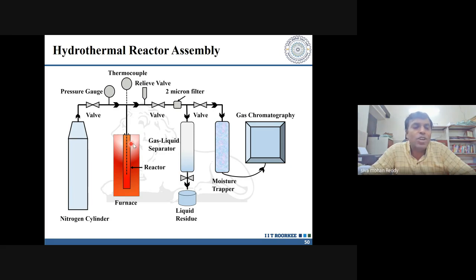Before we place the reactor inside the furnace, we make sure that the inlet valve and the outlet valve over here are closed. As a result, it forms a closed system, and when you heat it, the pressure is automatically built up inside the reactor. As soon as you are heating, the supercritical state is going to be achieved after some time. Once the supercritical state has been achieved, from the pressure gauge we would be able to understand what kind of pressures we have achieved.